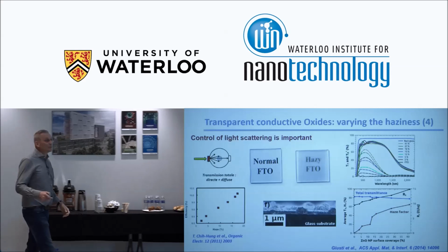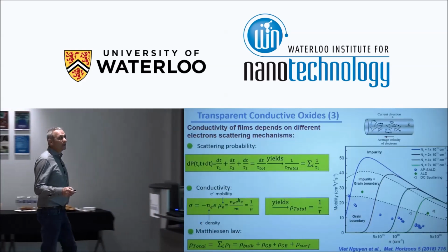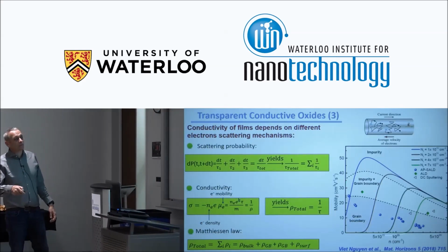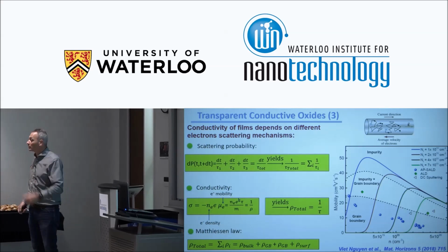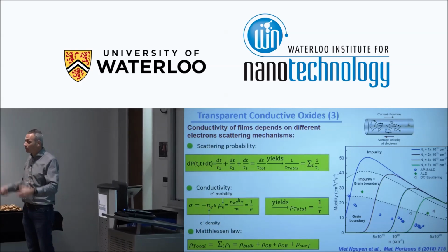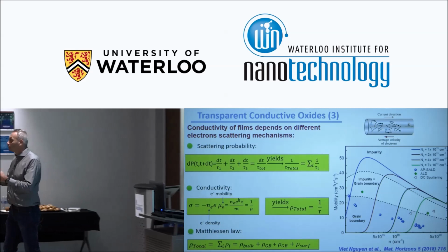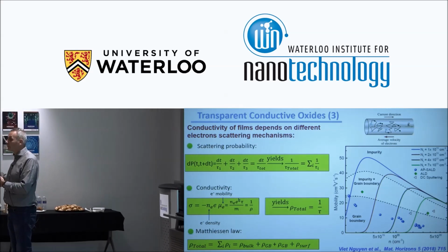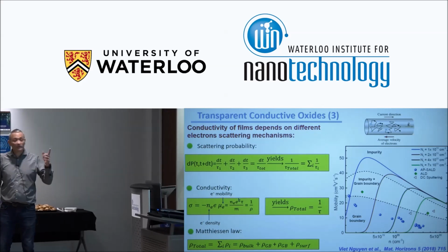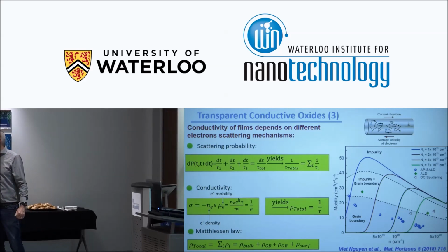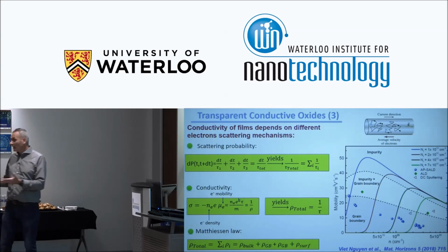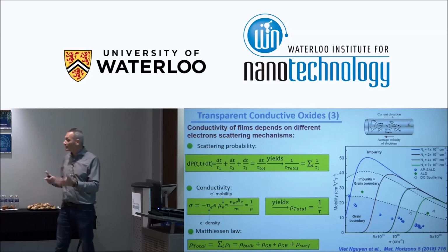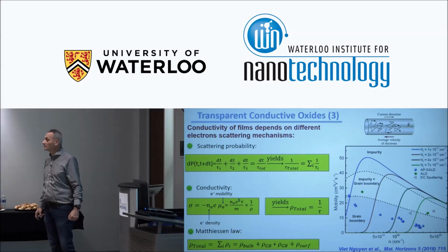Oh, yeah, we varied several parameters. In this case, we varied the doping level. We varied as well the thickness of the layer, so that changes the grain size, for example. And so you can tune the impurities or grain boundary scattering. And as well, we tried to UV treat these layers. So you can play with different parameters, either during the growth or making some post-deposition treatment. And afterwards, we are analyzing and trying to understand which is the main scattering mechanism.